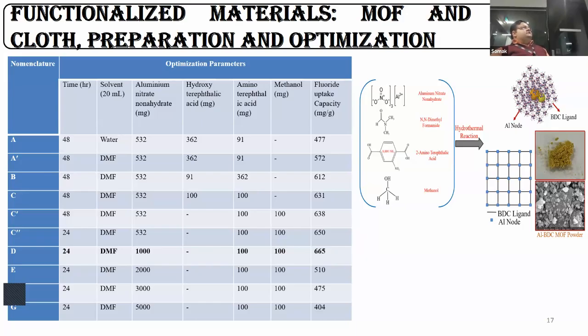So we instead used something for methanol. You can see over here, we carried out an analysis for the fluoride uptake studies. We were able to find that with methanol to amino terephthalic acid taken into account in a 1:1 ratio, the uptake capacity reaches 665 milligrams per gram, which is very high.